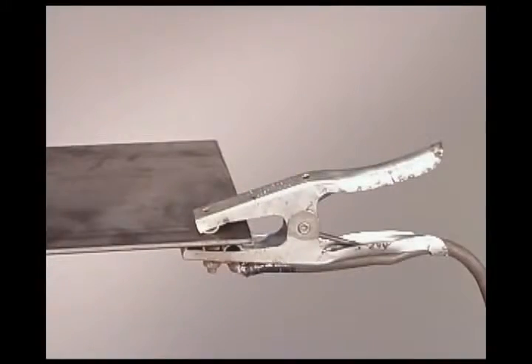Have a good clean ground. Use a short electrode stick out for a hot start. Maintain a 1/4 to 3/8 wire extension for consistent penetration. Back the gun away a little to cool the puddle for filling gaps. Push the weld to limit penetration and to see where you're going. Pull the weld for more weld buildup.